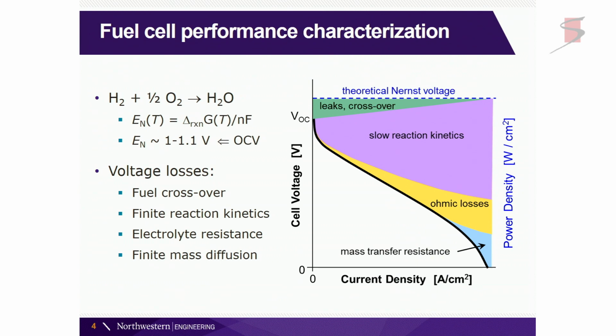But once you address that, then you start to draw the current, and now the voltage decreases because of things like the finite reaction kinetics. That's usually what we call our overpotential. And then as we start to draw more current, we start to see the impact of the ohmic resistance through the electrolyte, and at very high current densities, we start to see mass transfer resistance. The power density that we get out of this fuel cell is established by simply taking the voltage multiplied by the current density. So we get a power density curve that has this peak value at intermediate conditions.